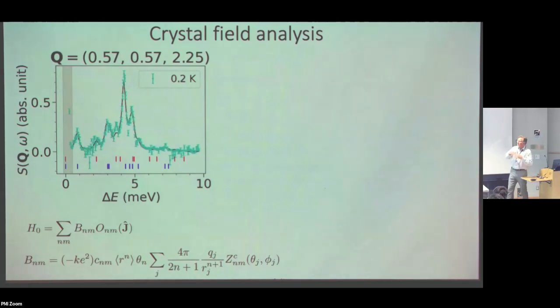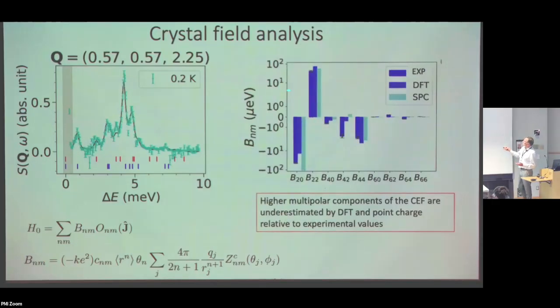And this was done really quite elegantly by Chris Ligoros. And it was a fairly large calculational activity. What I'm showing you here just cuts through as a function of energy at specific wave vector transfers, but we have the whole wave vector space accessible to us. And so all of the wave vector dependence has to be analyzed, and that will reveal the nature of the exchange interactions. So this is the crystal field Hamiltonian, which can be written in terms of these Stevens operators and tesseral harmonics. These are the, what's it called, expansion coefficients for the crystal electric field, and those we can extract from all of this analysis.